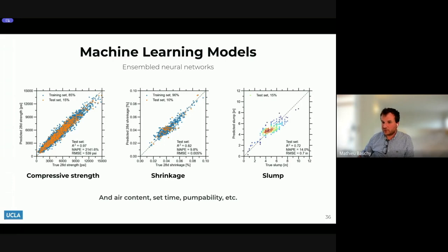And when it comes to concrete, if you measure the strength of concrete for the very same concrete, you will get different answers every time. For example, the strength of concrete typically varies with a standard deviation of about 500 psi. So the way we look at those models is we look at the accuracy, for example the root mean square error, and we ask whether the accuracy is comparable to the uncertainty of the measurement itself. And this is typically what we are able to achieve with those models.